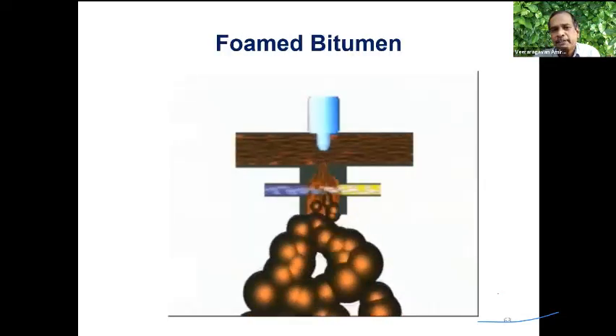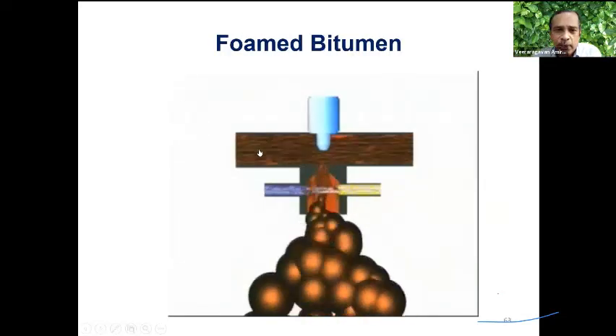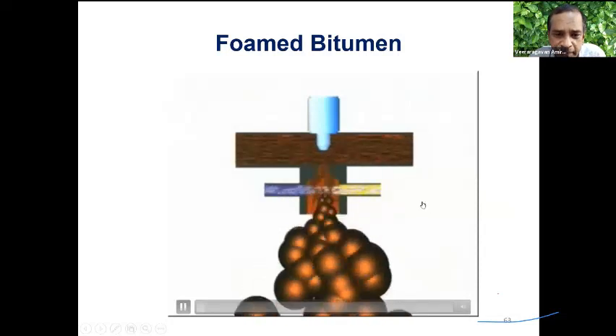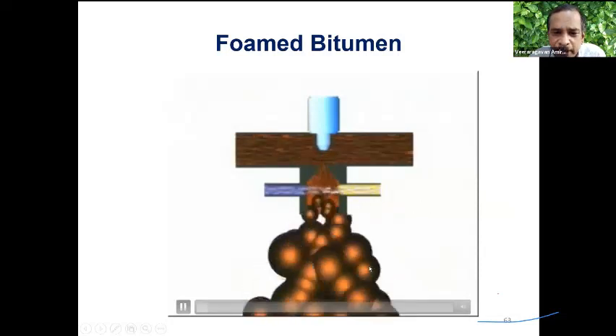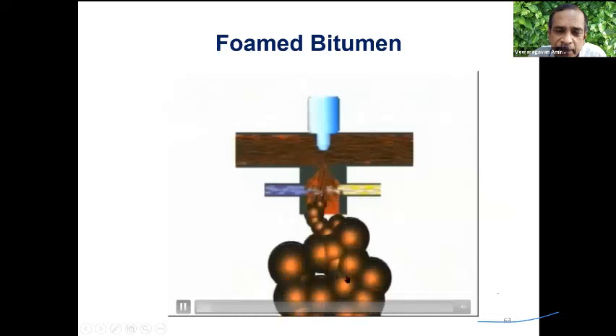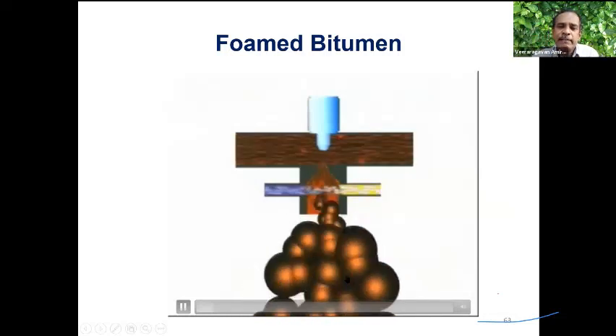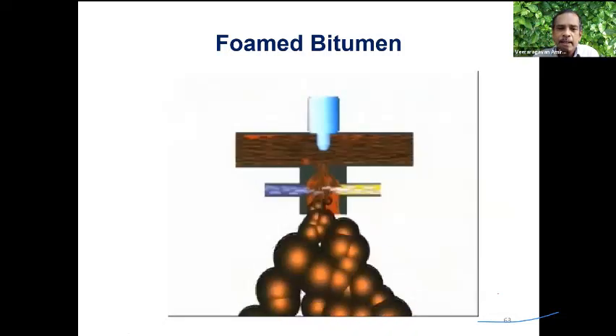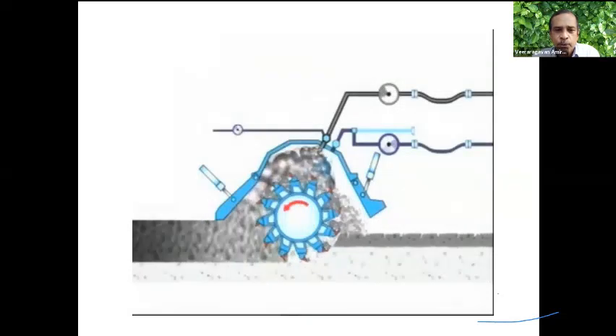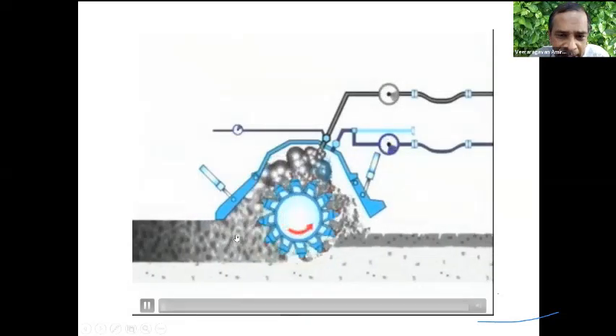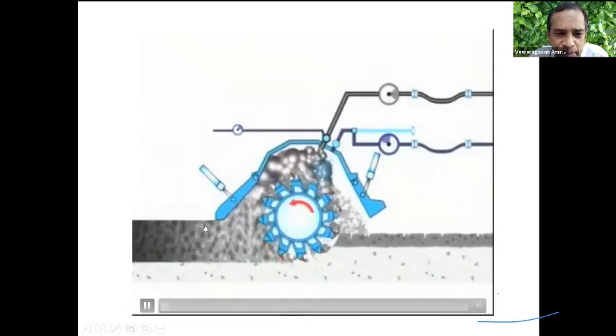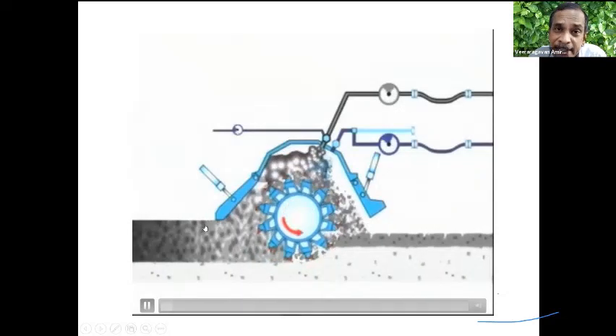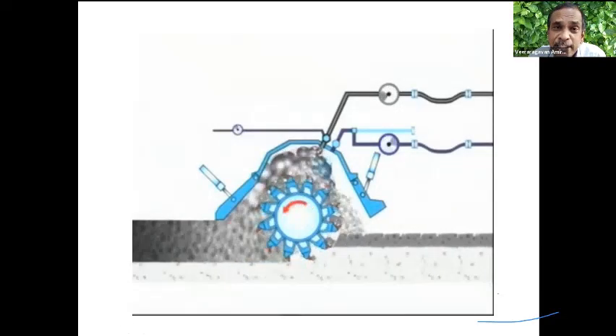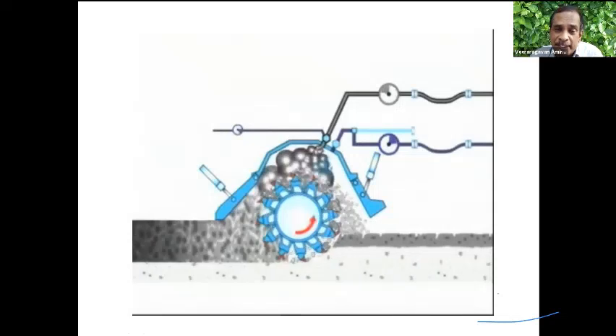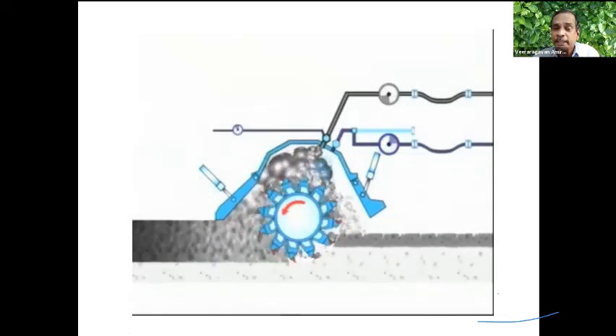This is what is called foamed bitumen. To the hot bitumen, I inject water, I inject air. The bitumen foams. When the bitumen foams and we add this foam bitumen to the milled material, it will mix the material which is being milled, and it's being laid. And so now you get an excellent base course, which is much, much better than a conventional granular base.